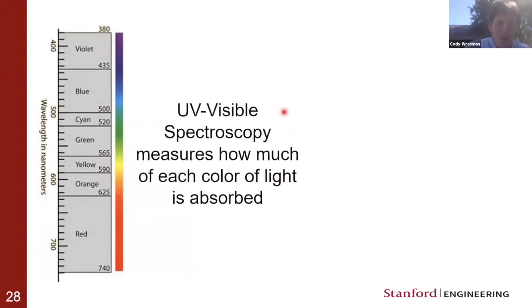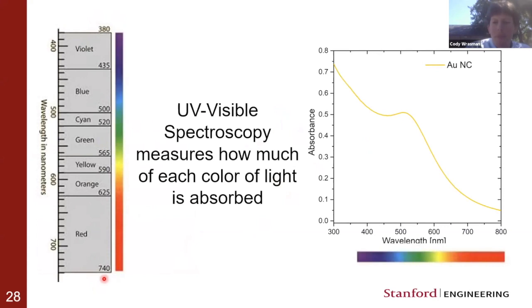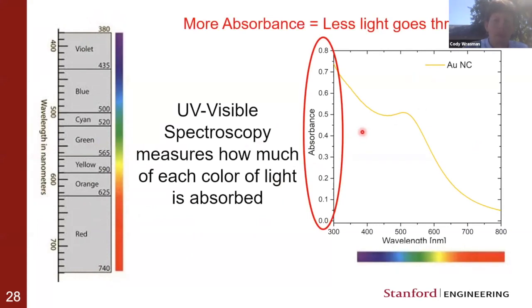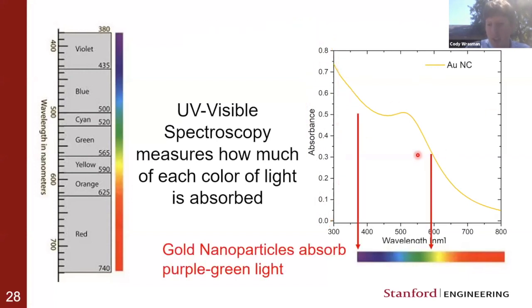The technique that we're using here is called UV-vis spectroscopy. We're basically measuring how much of each color of light is being absorbed. Here I'm showing you the scale of different colors and what wavelengths those correspond to. The reason that gold nanoparticles look red like they do is because they absorb rather uniquely. What's being shown on this graph is the amount of absorbance, basically what fraction of that color of light is being taken up by those nanoparticles. You'll notice that the absorbance of these gold nanoparticles is much higher in this purple to green area, leaving this red area open. That's why these particles appear on the red end of the spectrum.